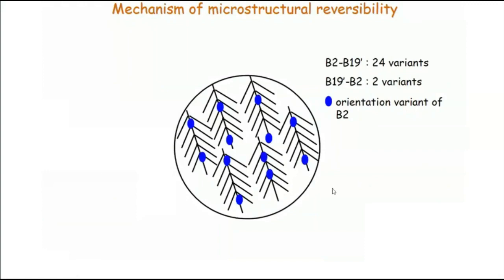So I will just start with this slide again, just to show you some of the evidence of this microstructural reversibility, because we made this claim that with a polyvariant microstructure like this, you can somehow get back to the situation where everything will coalesce and give rise to the original grain, despite the fact that it can give rise to different orientations. The challenge is this: when you get a microstructure like this, you get austenite nucleating at different points. Now, in the case of monoclinic, each of these crystals can give rise to two orientations. So all these orientations which nucleate at different points of the microstructure during the reverse transformation should give rise to the original orientation of austenite.